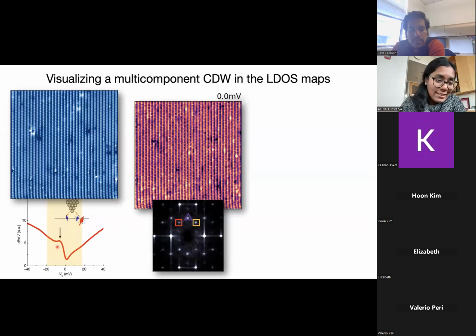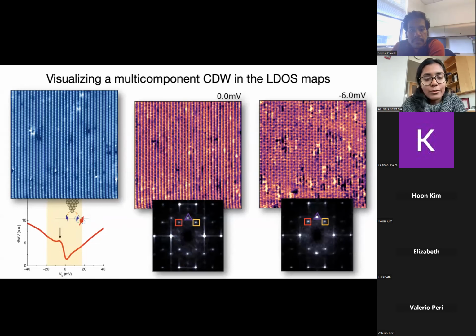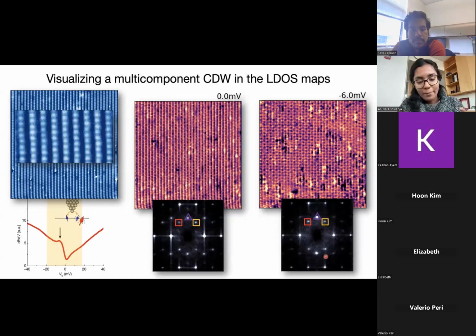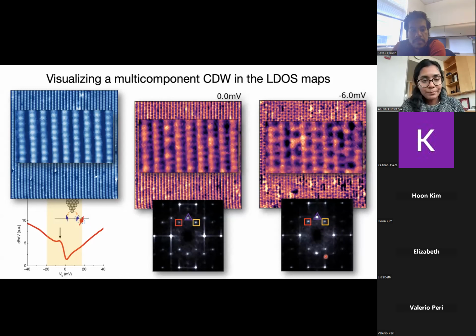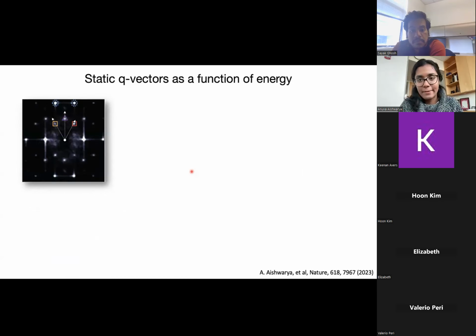We can also take a slice at the Fano peak, which is at -6 millivolt, and we see that it also shows the same peaks as the topography. We can also look at very high resolution atomic scale density of states maps. And what we see is that almost every alternate tellurium atom lights up along the chain. The reason I say almost is going to become clear in the next slide.